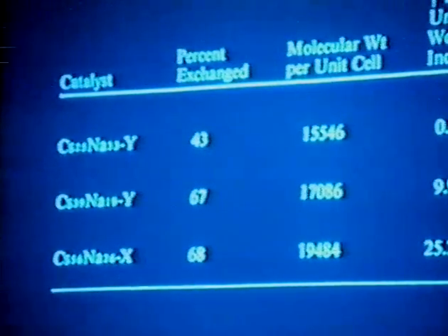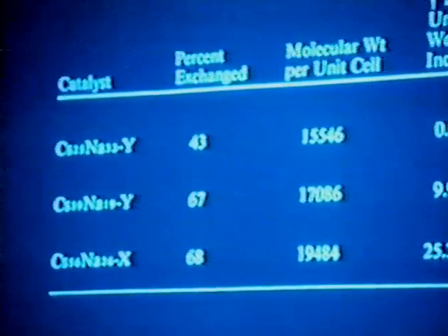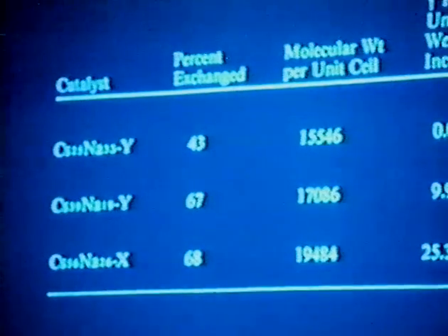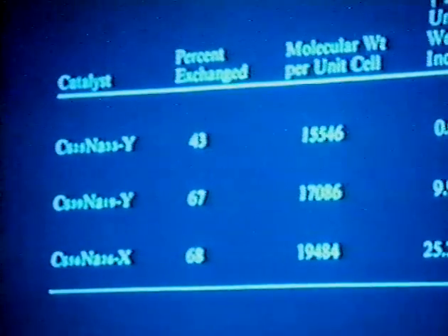During an impregnation with an aqueous solution of cesium acetate, there's a possibility that some of these sodium cations can exchange with the impregnated cesium acetate to form sodium acetate, and thus work against us as far as impregnation. So I chose a partially exchanged Y so that we have some available sodium cations as well, to see if in fact they are exchanging during impregnation.